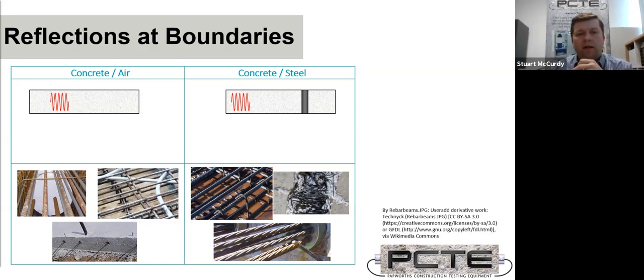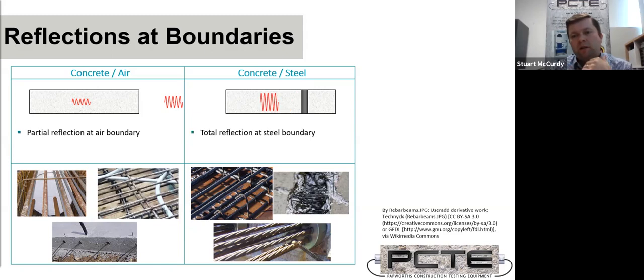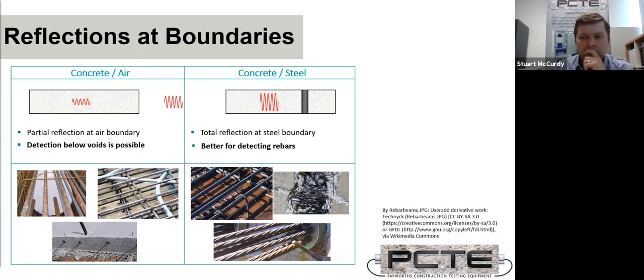Each material reflects a different amount of the GPR signal back. And that difference is what gives us our contrast on a GPR scan. So steel reflects all the signal back. That's why we get really sharp curved objects, those curves we showed you, or the red dot on the heat map. And it's also the reason that we can see the bottom of the slab when we change from concrete to soil or concrete to air.